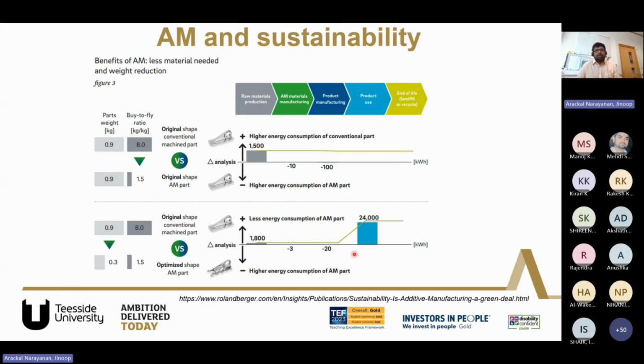So if you see a normal part and an additive manufactured part, you can see that the buy to fly ratio is significantly lower for an additive manufactured product as compared to a conventional part. So if you take an aerospace bracket as an example, the buy to fly ratio is 8 for conventional manufacturing, while if you use additive manufacturing, the buy to fly ratio is only 1.5. So if you buy 8 kg of material, then you can produce 1 kg of final product, while with additive manufacturing, you can use 1.5 kg of raw material to produce 1 kg of final product. Because of this high material intensive process in conventional manufacturing, the energy consumption has gone very high for conventional manufacturing. And so if you see, additive manufacturing has got a very high benefit over conventional manufacturing in this case.